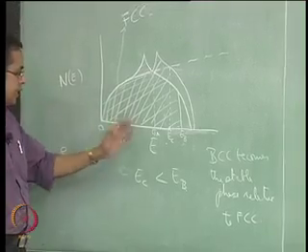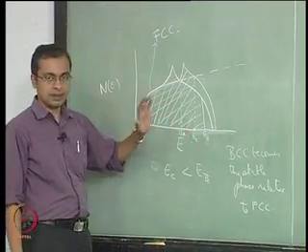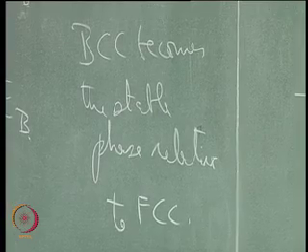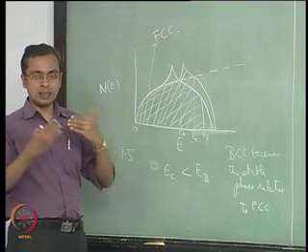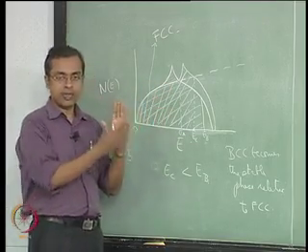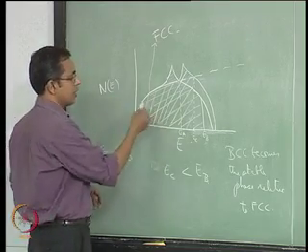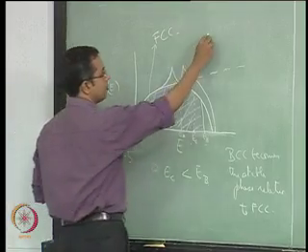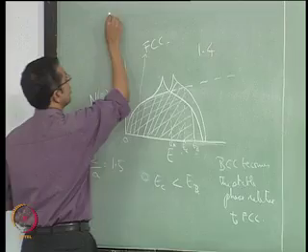Okay. So we see clearly from the diagrams that we have drawn for these systems, from all the understanding that we have gained in this course, how a certain type of phase change occurs as a direct result of what we can see on these diagrams. It turns out that this ratio for these systems works out to about 1.4. If E by A is less than 1.4,